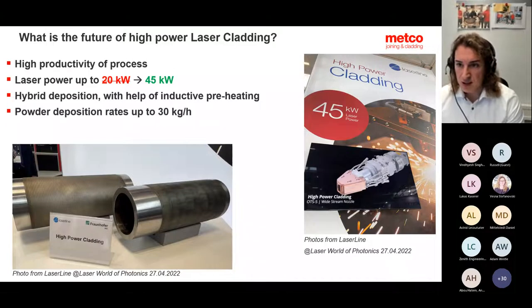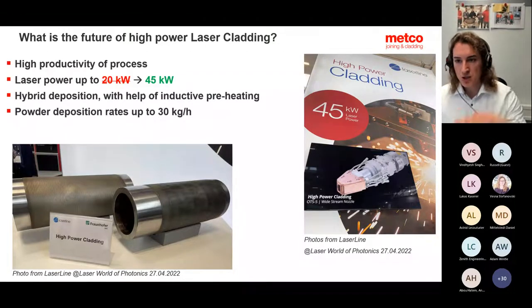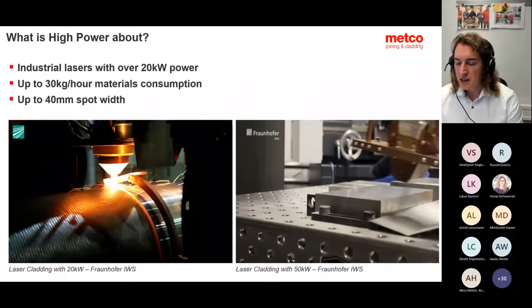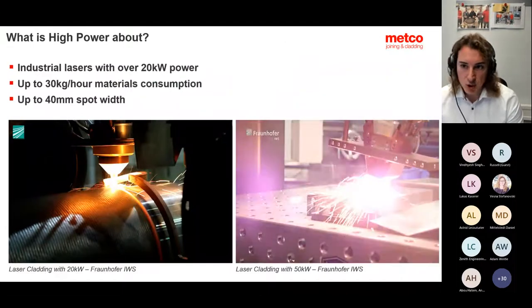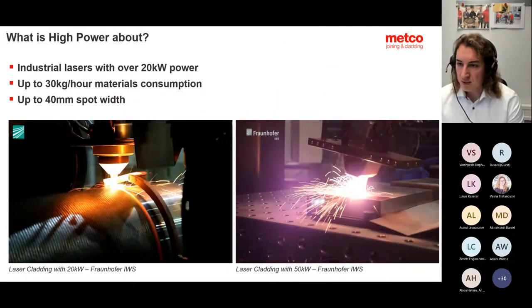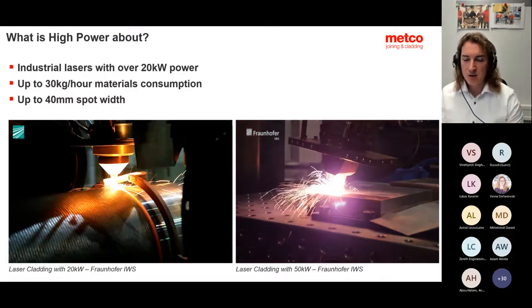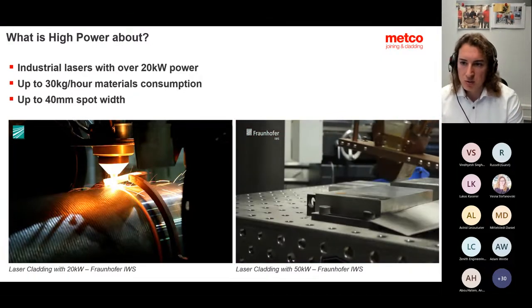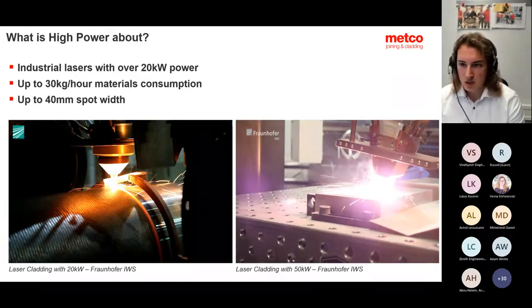What is also surprising is that the surface roughness is amazingly smooth, even for a laser cladding process, and the interaction of your melting bath with the substrate is pretty impressive. So your dilution remains under 5%. Even working with these extremely high power lasers, you still do not introduce too much heat to your surface.